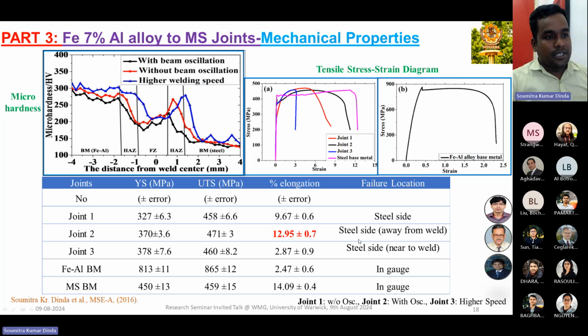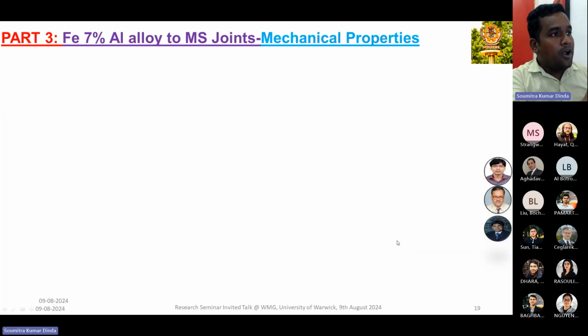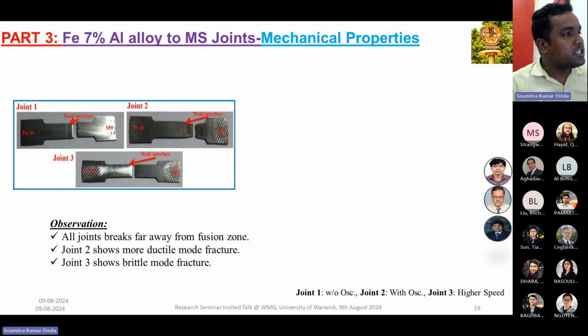And see where these samples break. Not even in the HAZ, not even in the fusion region. If you see the image of this tensile broken sample, this is the whole gauge length, and this is my fusion area, and the sample breaks far away from the fusion zone. That means our weld joint is strong enough, or stronger than our base metal.